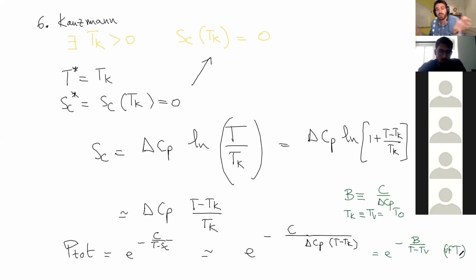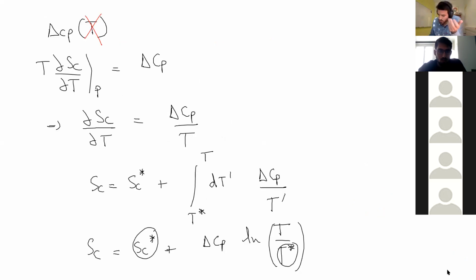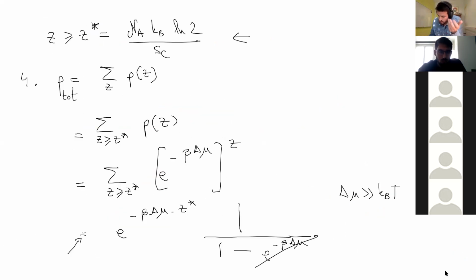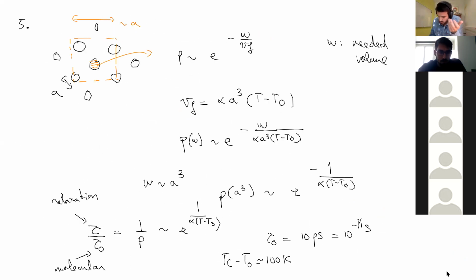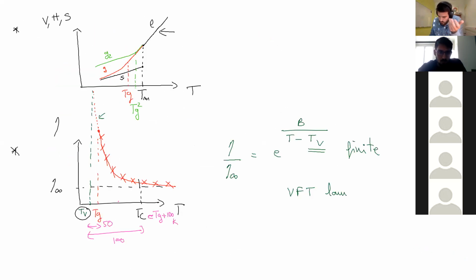But those might all be equal, and so there should be a real phase transition that is occurring at a point TV, but that you cannot see because while reducing the temperature, at some point you reach TG, which is a bogus object, purely kinetic, and the system becomes so slow that you're not able to find the equilibrium, you're not able to find this TV point because you cannot measure any relaxation. It's too long for humans.